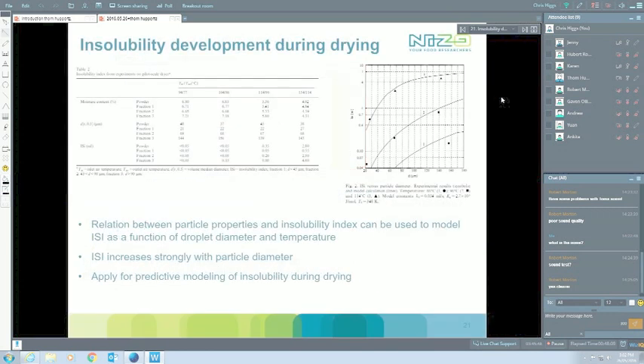And since it's very much related to heat load, and the heat load is very much related to how the powder particle will go through the dryer, what we see is strong correlations there with particle size as well. What we typically tend to see is that bigger powder particles tend to give higher insolubility. They take longer to dry. They get a higher heat load in general. They have a much higher chance of developing insolubility.